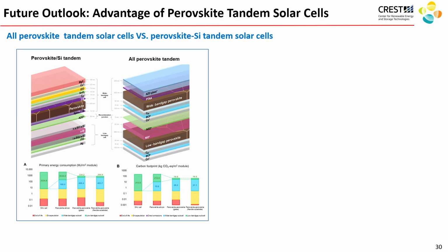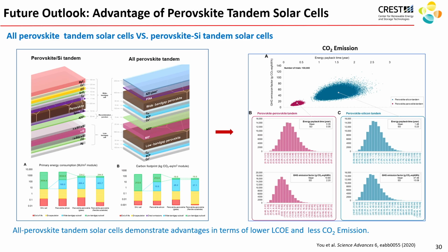There are now two kinds of tandem solar cells: there's silicon with perovskite, and there's perovskite with perovskite tandems. At the moment, silicon with perovskites seem very interesting because they integrate very well with current technology and current manufacturing methods. However, we believe over time, perovskites are going to win out, because they use 1/4 of the energy input to make, and their potential limit for efficiency is much higher. So we see that this is a very hot area; with perovskite, there's a lot more to do, but the potential is much larger.